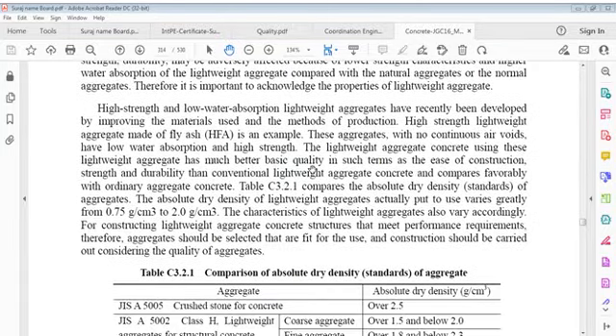High strength and low water absorption lightweight aggregates have recently been developed by improving materials used and methods of production. High strength lightweight aggregate made by fly ash, HFA, is an example. These aggregates with no continuous air voids have low water absorption and high strength. Lightweight aggregate concrete using these lightweight aggregates has much better basic quality in such terms as ease of construction, strength and durability than conventional lightweight aggregate concrete, and compares favorably with ordinary aggregate concrete.